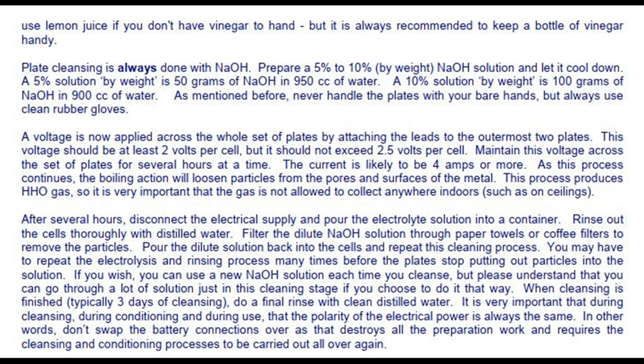A voltage is now applied across the whole set of plates by attaching the leads to the outermost 2 plates. This voltage should be at least 2 volts per cell, but it should not exceed 2.5 volts per cell. Maintain this voltage across the set of plates for several hours at a time. The current is likely to be 4 amps or more.